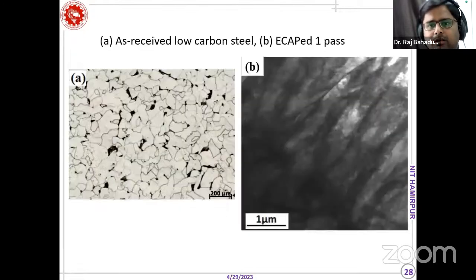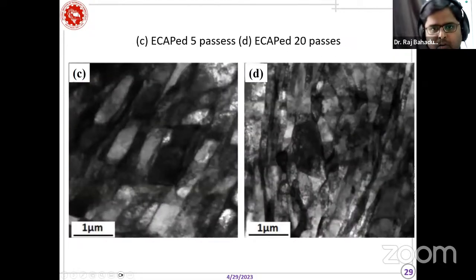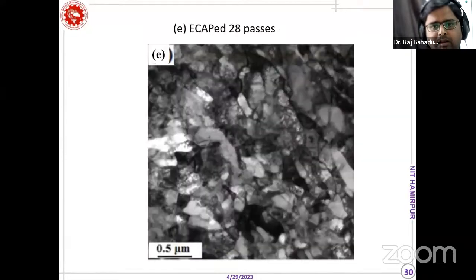Now coming to the results of this ECAP material. This is again an optical micrograph of annealed low carbon steel. We have deformed that material, and you can see the dimension of the different thickness of these grains, very small, and we keep on deforming the material by these techniques. Then you will find the grains are more and more fine after each pass. This is the final micrograph after 28 passes of the low carbon steel.